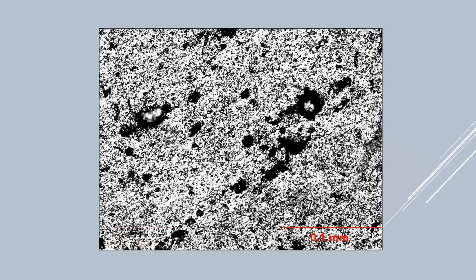That's why they got cracking in the heat affected zone, is their welding procedure was completely inadequate for something of that high carbon content. That's a little bit better picture of it there, but you can see lots of little iron carbide particles there. And you can see also that my in-situ replica pulled up some inclusions in that steel. And the inclusions are probably manganese sulfide or silicate. And there's a really big one.